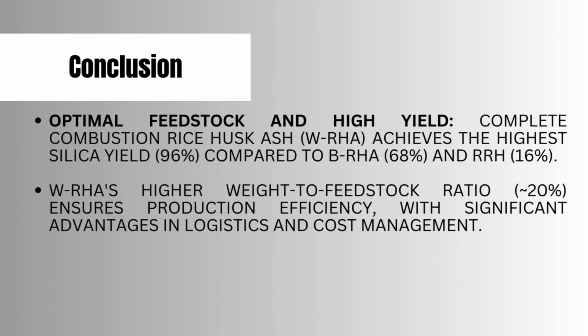So the conclusion for the project is optimum feedstock and high yield. Complete combustion of the rice husk ash, which is the white rice husk ash, achieved the highest silica yield, 96%, compared to the black rice husk ash, 68%, and the raw rice husk, which is only 16%. White rice husk ash, with a higher weight to feedstock ratio of around 20%, ensures production efficiency with significant advantage in logistics and cost management. That's all for this project.